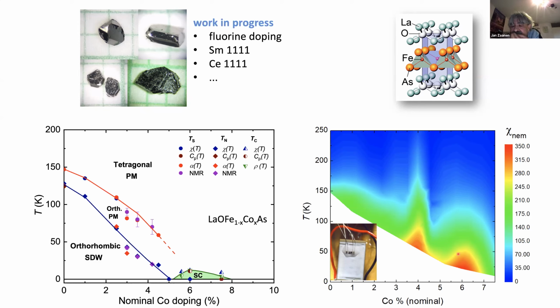Could that be? First of all, these systems do not show a first order transition. So they're already second order in the parent compound. First order is, I think, in barium 122, in these compounds it is second order. But I agree, yeah, the tetragonal to orthorhombic structural transition is second order, at least if you believe our thermal expansion and thermodynamic properties. But nevertheless, you're right. I think it is basically an electronic instability, which we probe via these strain dependencies.